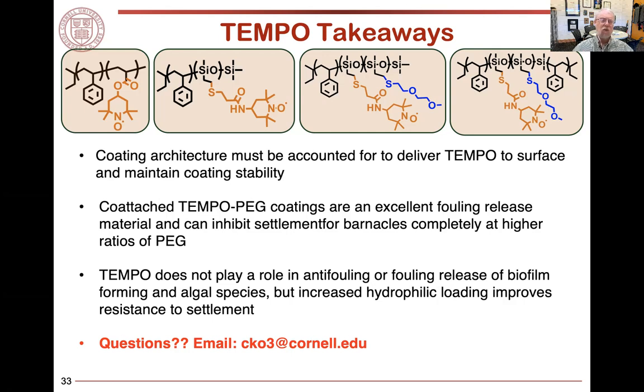The co-attached, the combined TEMPO PEG coatings are excellent fouling release materials, and they can and do inhibit settlement for barnacles and do a very good job at the higher ratios of PEG. And the TEMPO does not play a detrimental role in the biofilm formation in algal species, but the increased hydrophilic component helps out.